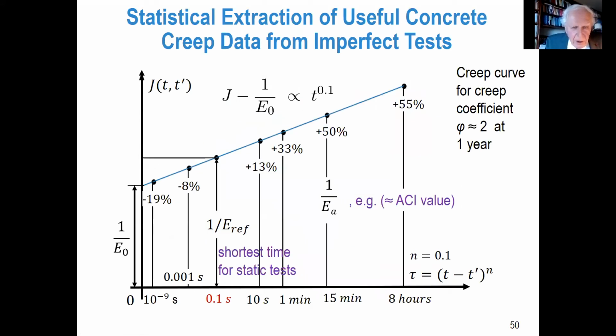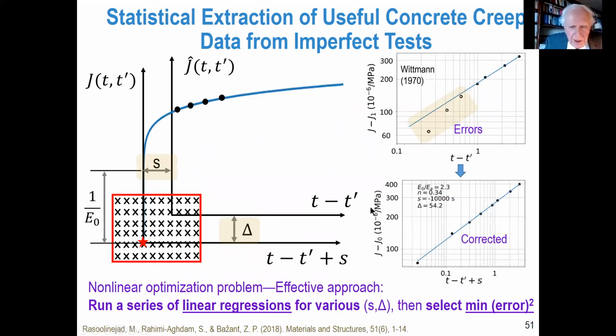If you take it in a log scale, this is a typical creep curve in a semi-log scale. No, wait a minute. This is a log scale, 0.1, because it's a straight line. So here is 1/10 of a second. This is the range of damping in vibrations, complex modulus, viscoelastic. So it's actually also known. It continues as a straight line, and here up to what is in practical testing.